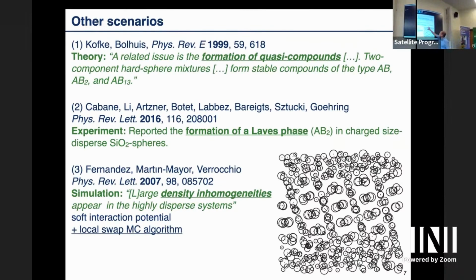So here there's some disorder, but that actually looks already pretty ordered. And if you compare it to what we saw before, it almost looks like there is some crystal forming. But this was a very small part of the simulation, and they didn't really know what's going on. And they used the soft interaction potential, so not quite the hard potential. But what they also did to get here, they used something called a local swap Monte Carlo algorithm. So that means they swap particles.